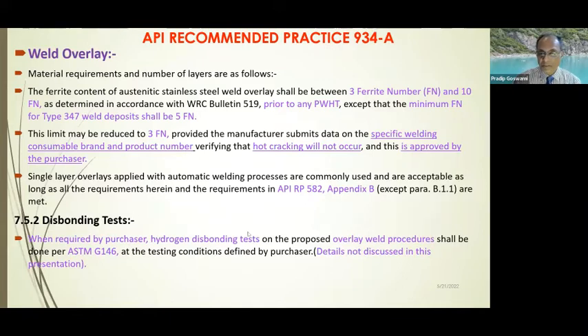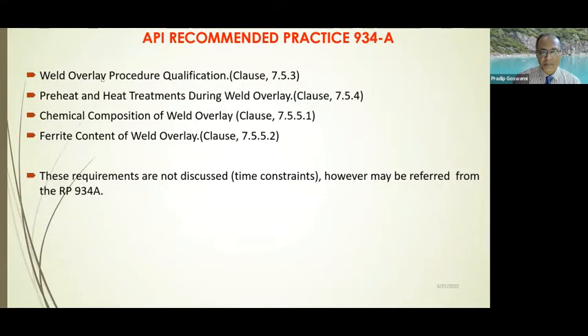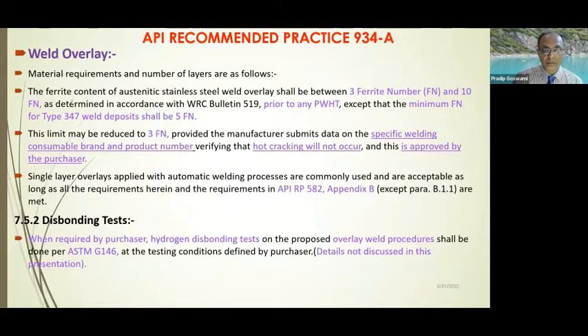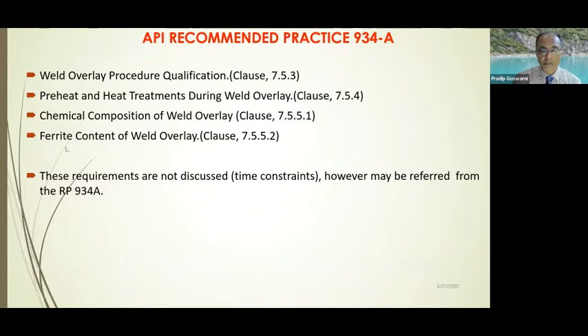Disbonding test: when required by the purchaser, hydrogen disbonding test is needed for the overlay weld procedure. That's a very specific test, with details mentioned in ASTM G146, and I'm not going into the details of that. But as a matter of fact, the disbonding test is quite an important test for the weld overlay, and they have to pass that. And typically, as I mentioned before, welding consumable procedure qualification, preheat, heat treatment during weld overlay, chemical composition of the weld overlay, then ferrite content of the weld overlay. These are the typical requirements which have to be fulfilled during the procedure qualification as well as production welding of these welds, on these equipments, I would say.